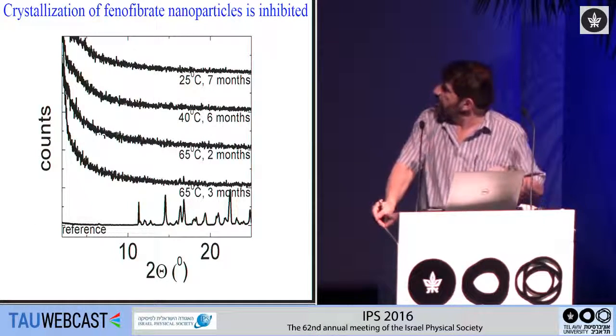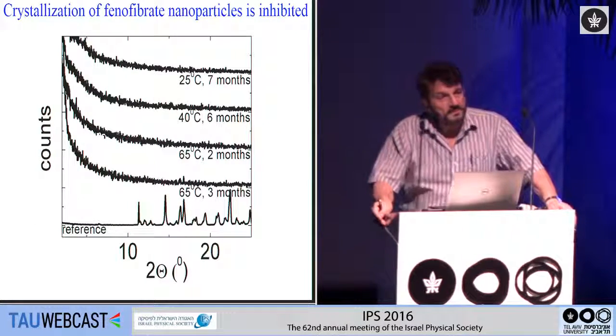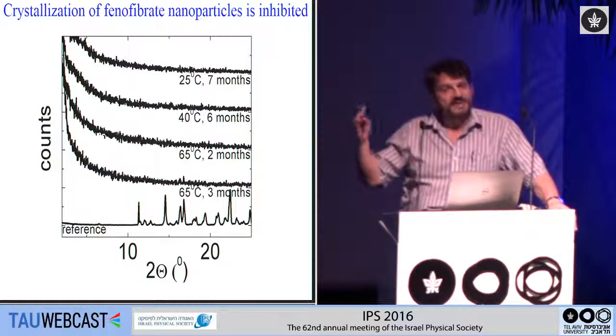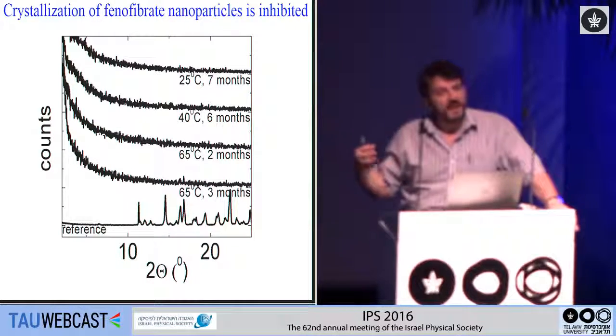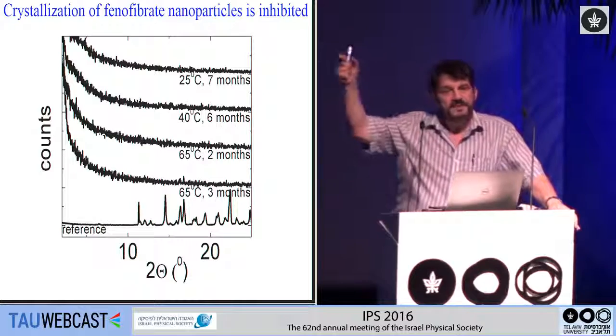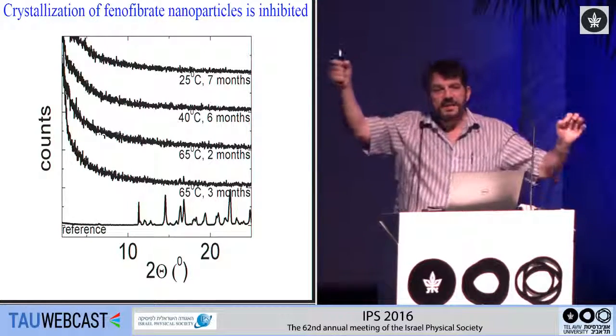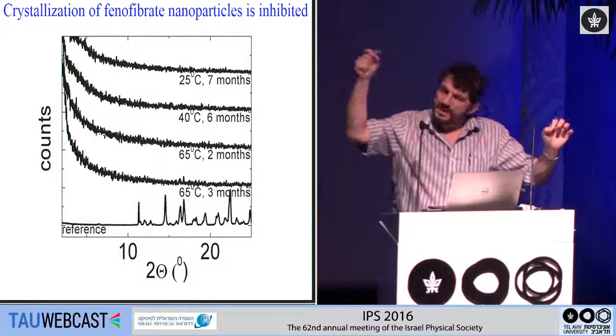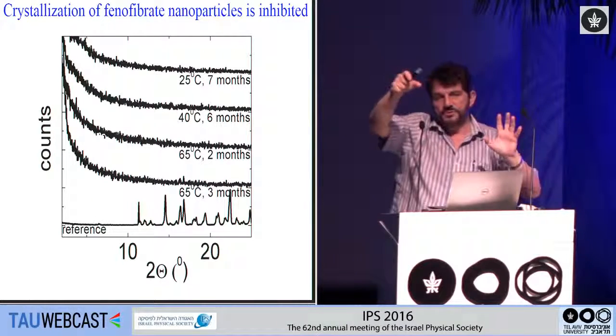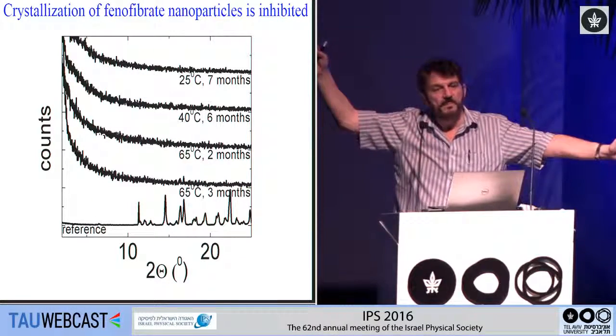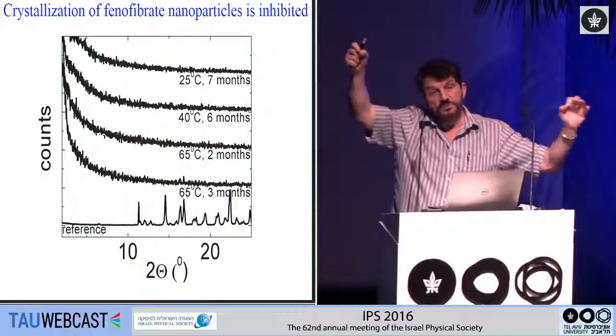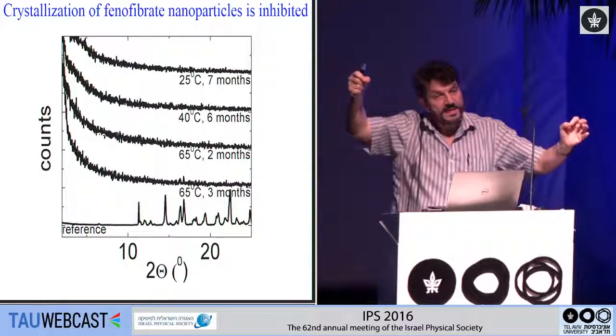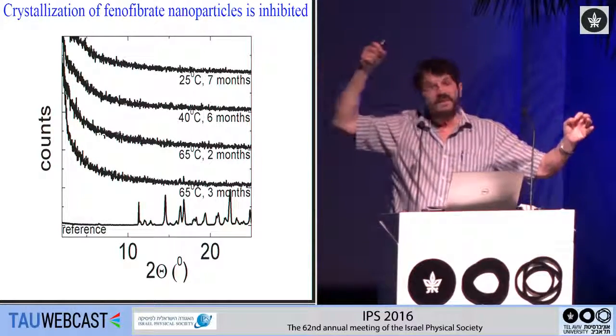You can actually look at the stability of the amorphous material, and it remains stable over long periods of time. The reason, of course, is that because it's amorphous, if something turns into a crystal, it's only that one particle that crystallizes. As long as you can keep the particles separate, that is, you keep them somehow stabilized, then they'll crystallize, but they take forever to do it.